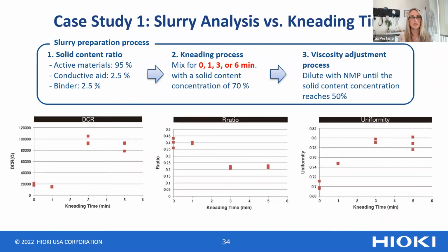And here are the results. On the left, you have that total resistance value, which you can see is low at the beginning for 0 and 1 minutes. You have low resistance of the slurry, and then it increases after 3 minutes. And then for the R ratio, you see that percentage starts out pretty high and it decreases a little bit as you mix it. And then the uniformity, you can see it increases. So that solution is becoming closer to an ideal capacitor type of situation.